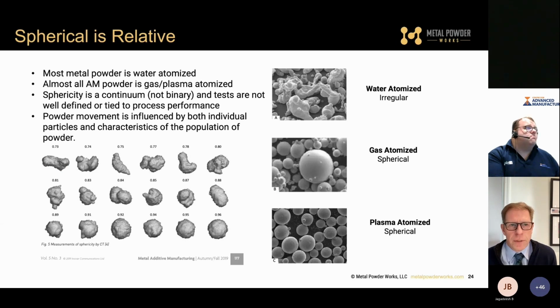So, when we talk about spherical and non-spherical, I think we're starting to overcome the desire that super spherical is really desirable, because now we're seeing that denudation actually impacts the ability for us to retain some tolerances and surface finish. And so denudation simply is, think of it simply that if it took very little energy to get the powder into position, which we all like, it also means that it takes very little energy to get it right back out of position. In any additive process, you're putting a force on that powder. So as it's sitting in a bed and the laser is moving around it, the laser is exerting a force on the powder. This feeds the technical term of denudation, which is the powder moving. So it's no longer where you want it to be. It's partially the reason why we see spatter in some of these processes.